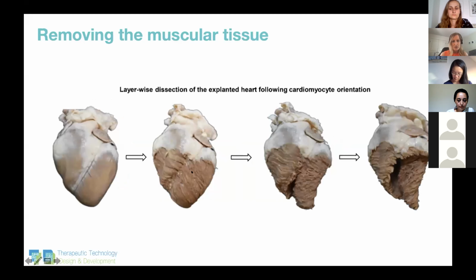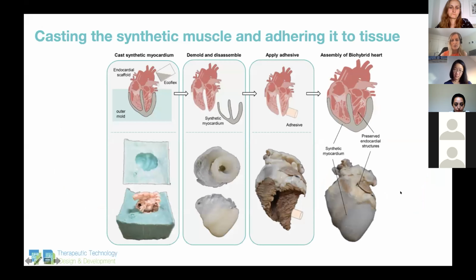Then we go through this dissection procedure, which is a very careful layer-wise dissection of the explanted heart. And you basically bluntly dissect in a manner that follows the cardiomyocyte, or the muscle fiber orientation, which allows you to dissect it in a very predetermined manner. So you're left with this left ventricle that has no muscular tissue surrounding it anymore. And the first thing we wanted to do was see if we could replace that muscular tissue with just silicone, just passive silicone, without any actuators or robotic components. So we placed the dissected heart back in the outer mold we made in the first place, and we filled the gap that had been dissected with silicone. So you essentially recreate the ventricles that you dissected with the silicone structure.